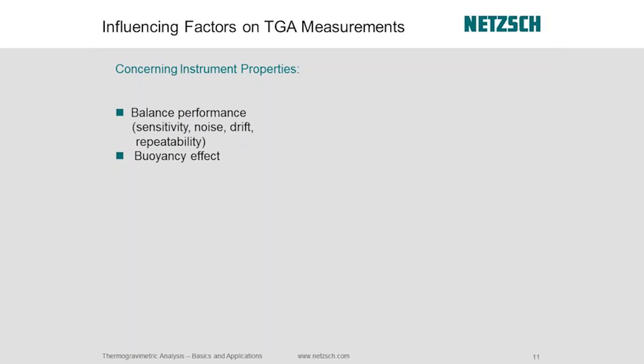So that's kind of a normal behavior as time goes on and temperature in the laboratory changes. One of the secrets to minimizing drift with the NETZSCH instruments is we use this recirculating chiller, and that stabilizes the electronics throughout the day. So if you've got temperature changes in the room while you're making a very sensitive TGA measurement, you want to make sure that your system is as drift-free as possible. And that's done both through the mechanical design, but then also through the electronic recirculating chiller.